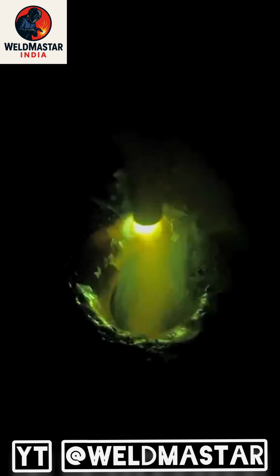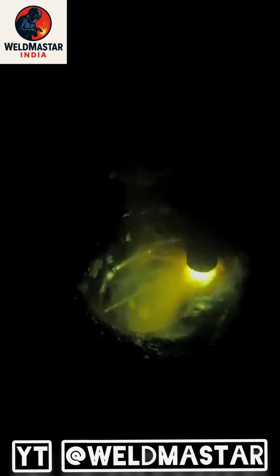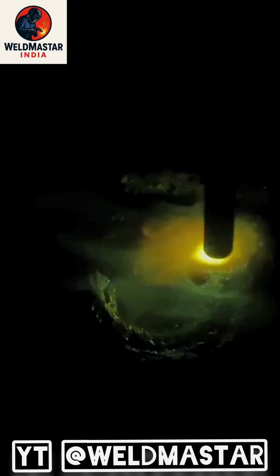When welding, keep the arc low and stable. Do not lift the arc too high. If the arc is too long, the molten pool temperature will rise rapidly, which can cause metal to flow downward and create defects. As you can see, by using this gradual, heat-controlled hole-filling method, the hole becomes smaller step by step. This is the correct and practical way to repair holes during ordinary welding work.